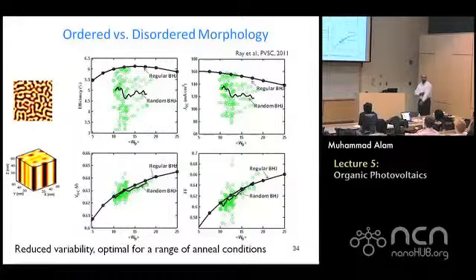That will be fine because that shows how much you could get in principle. But when you are going to connect a bunch of them in series and have a technology where you want huge volume, the efficiency you are likely to get is the average of them, if not lower. So ordered structures make a lot of sense, because in an ordered structure there is very little fluctuation, and it is always connected to the right contacts, so you can get relatively high efficiency and not suffer from this variability problem.